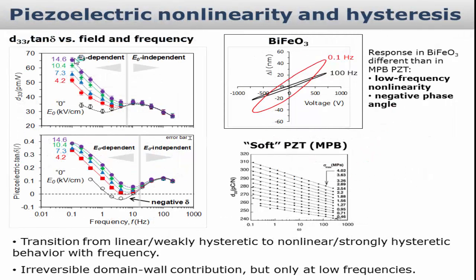So the next parameter that's usually used to measure piezoelectric response is the amplitude of the electric field. Here are the same curves as before, D33 and phase angle as a function of frequency, usually with the same technique. But here we change the amplitude of the sinusoidal electric field in the whole frequency range. And you can see that we have a strong dependence of the piezoelectric coefficient and piezoelectric phase angle on the amplitude, which tells you that basically you have some nonlinearity coupled with hysteresis. And this is typically attributed to the irreversible domain wall contribution, which is quite extensive for macroscopic properties in BiFeO3.